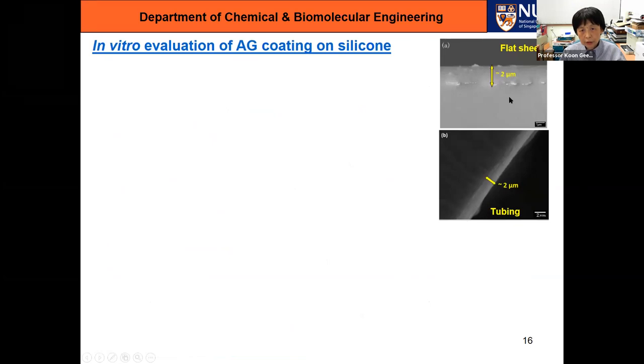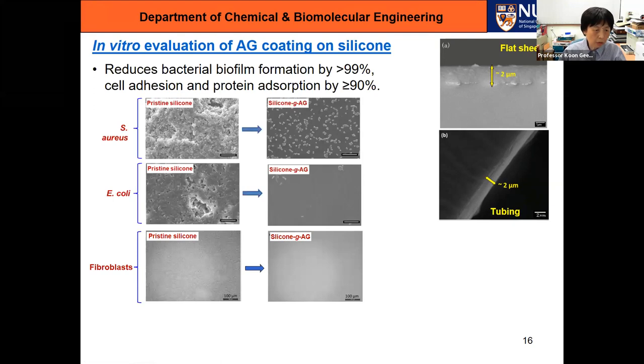This is a flat sheet, and this is the inner part, the intraluminal surface, of a tubing. In both cases, we coat 2 microns. For the flat sheet, we use plasma and UV. For the tubing, we use ozone and heat. So both can be done, and as we can see here, in both cases 2 micron coatings can be obtained. This shows the results.